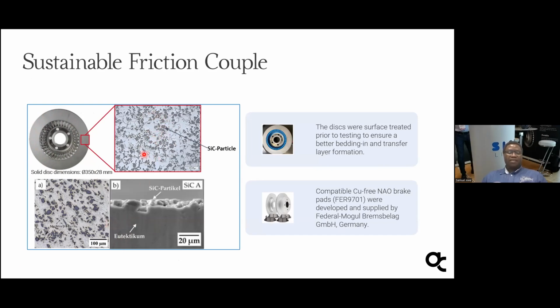Before the test, the surface, the friction ring, is pre-treated. We have two techniques of doing that, either through chemical etching or laser texturing. The essence of doing this is to improve the bedding in, that is the transfer, at the beginning of the braking application, to improve transfer of tribofilm on the surface. So that is done, and these were done together with the compatible copper-free NAO pad developed by our partner, Federal-Mogul.